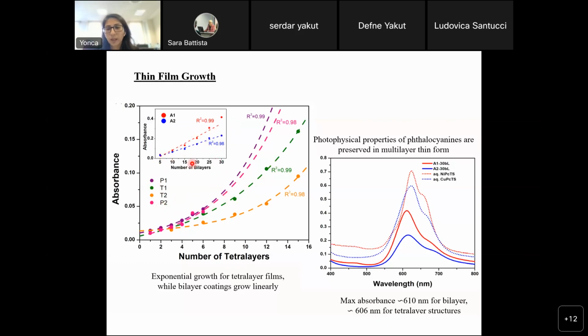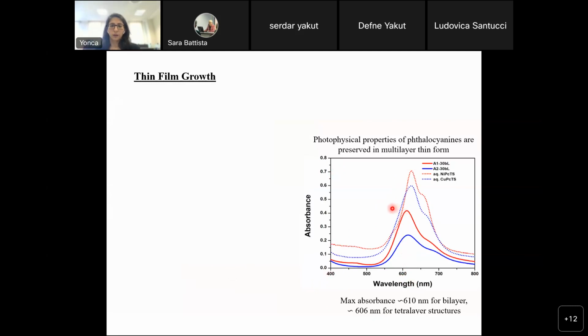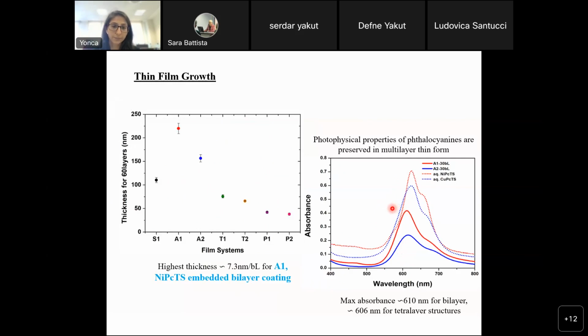And I also checked the photophysical properties, and they totally match with the aqueous forms, and they preserve the Q band at 600 nanometers for all structures. And in terms of thickness, what's interesting is that the bilayer structures, no matter which metal you have, have the highest thickness overall. So you can get 200 nanometer thickness with bilayer structures. But once you switch to tetralayers, then you'll have a decrease in thickness up to 40 nanometers or so. Just to make a note, overall all thin films have the same number of layers. Overall, they have 60 layers at the end.